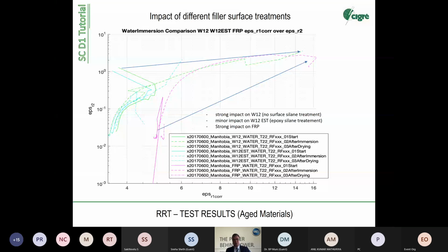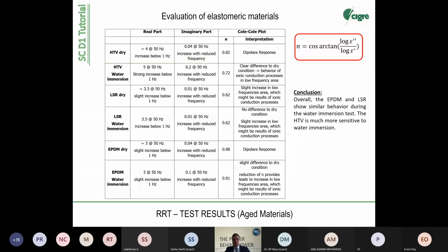Elastomeric materials. So this is an evaluation with an n mechanism or n procedure. So we see in most cases dipolar response in the dry conditions. And we see a start of ionic conduction. Lowering the n value means we are going into ionic conduction. We are dissolving alkaline ions and we are reducing n. It's also a good confirmation here that the LSR stays the same. It's not changing because there are fewer alkaline ions inside.